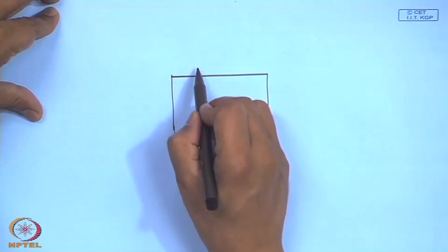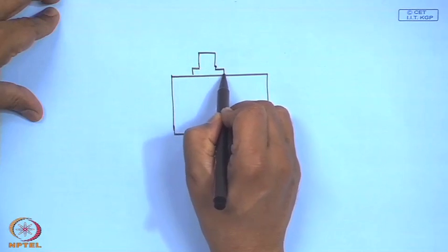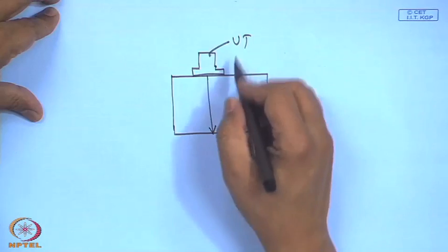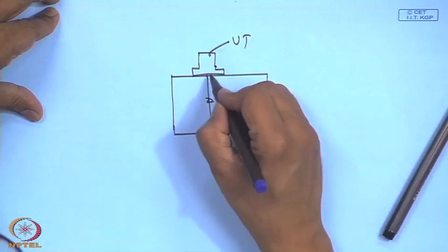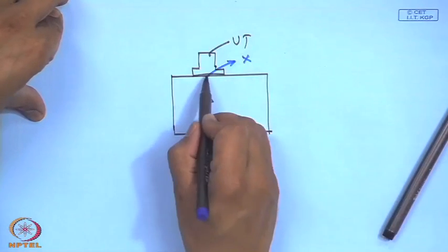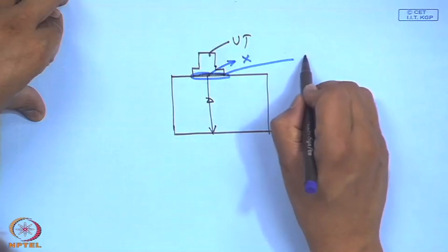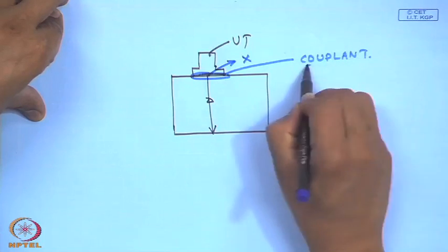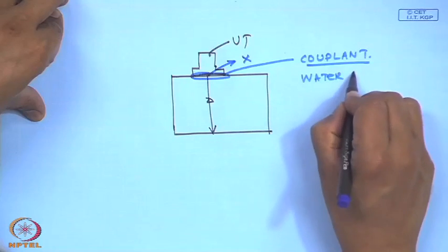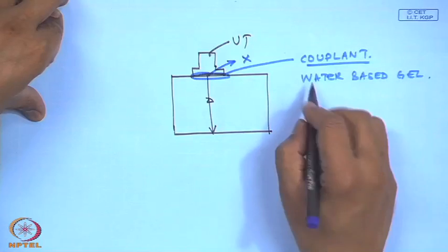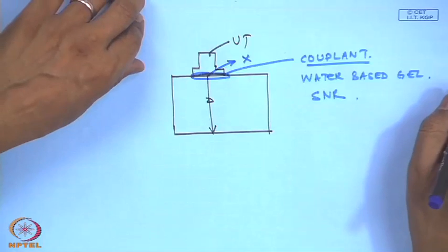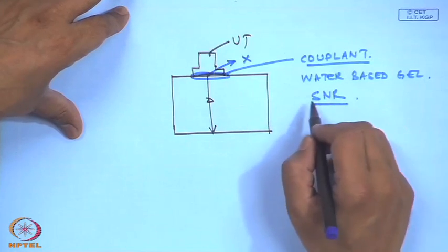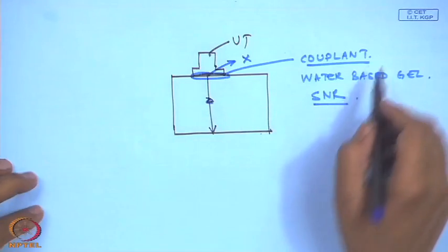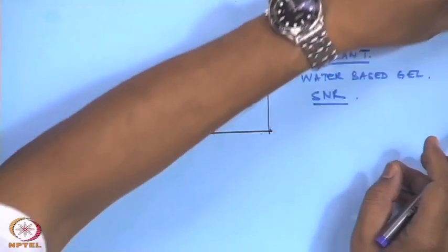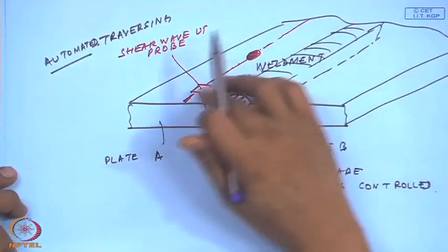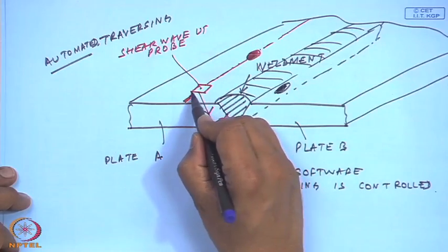Another very important aspect while doing such ultrasonic probing is, how do we ensure that the ultrasonic wave which we have generated is actually going in and getting reflected from the defect, and not getting reflected from this surface? To ensure that, usually a couplant is put, and this is nothing but a water based gel, so that a good high signal to noise ratio of the ultrasonic wave is generated, and all the energy of the ultrasonic wave gets transmitted to the medium. So this is one important thing. In this case, no special treatment of the surface is required, apart from that a layer of couplant is to be put.